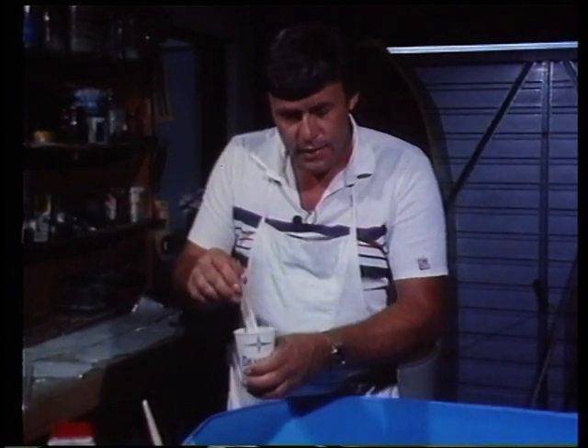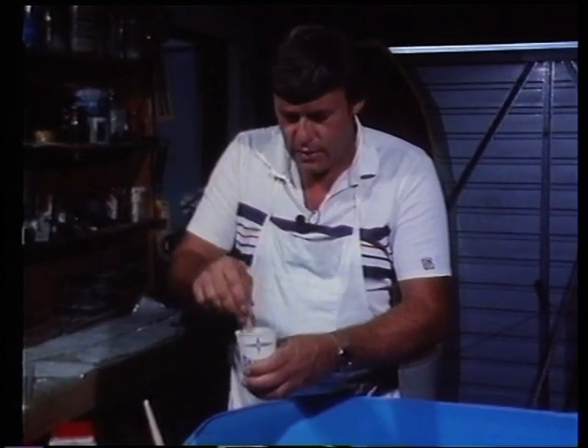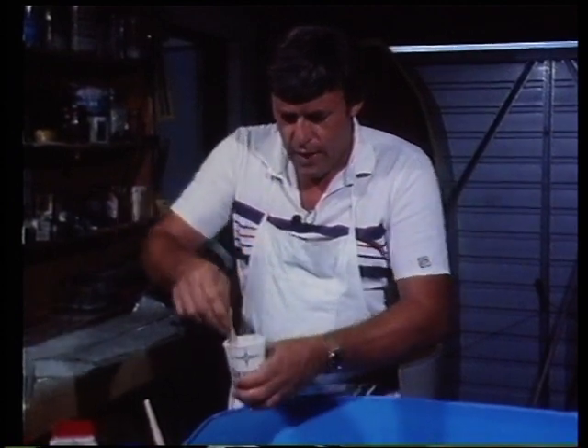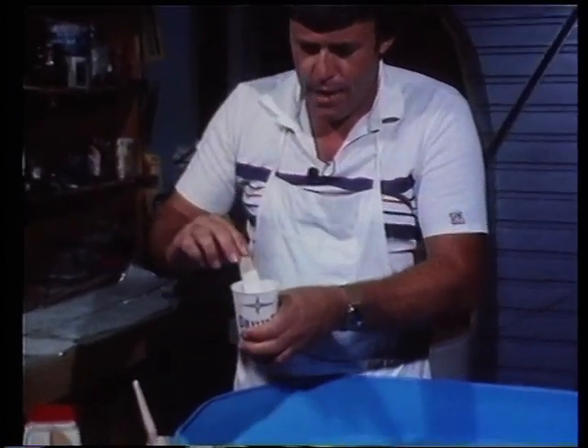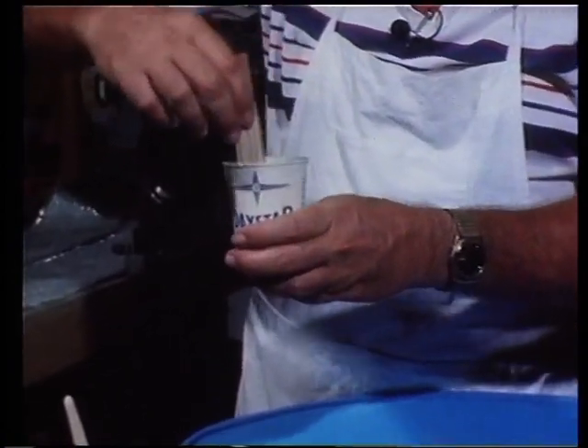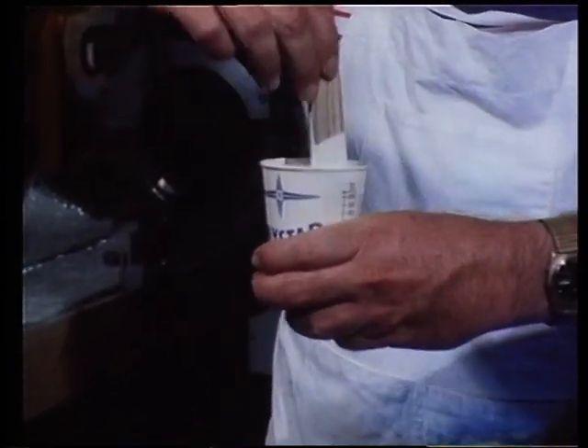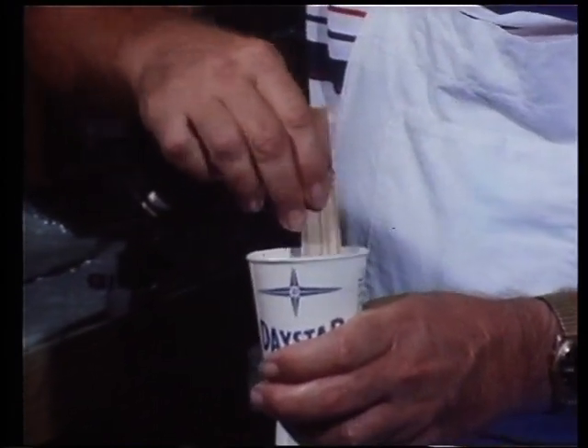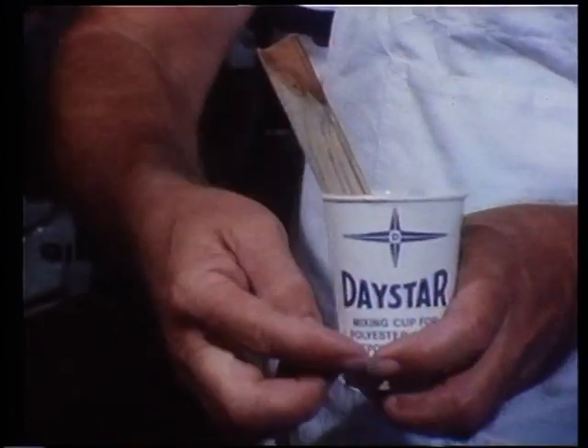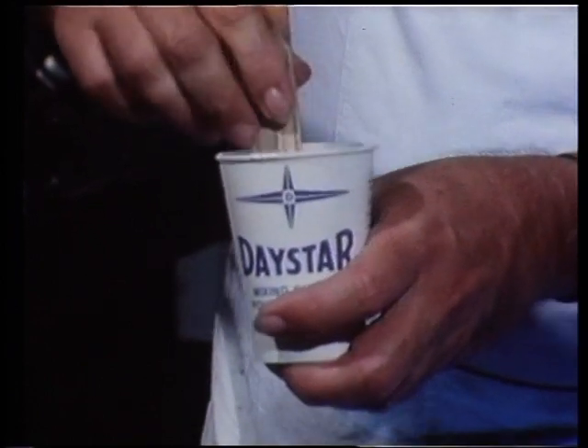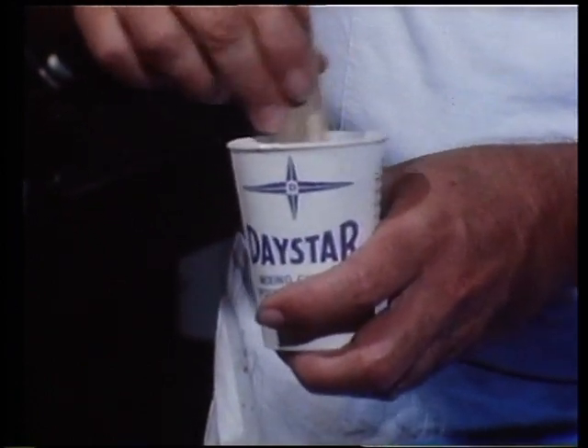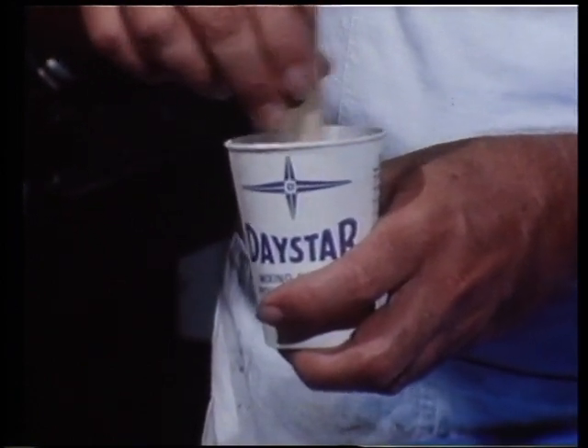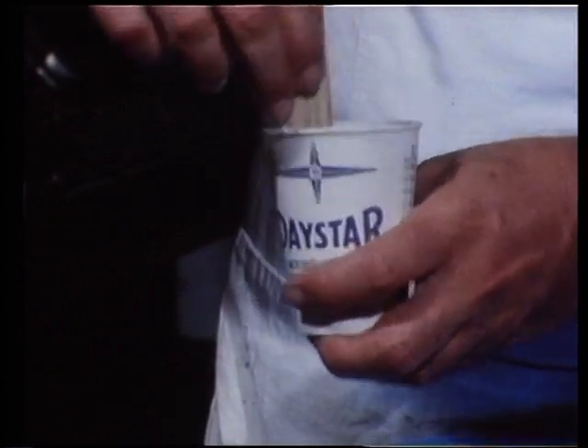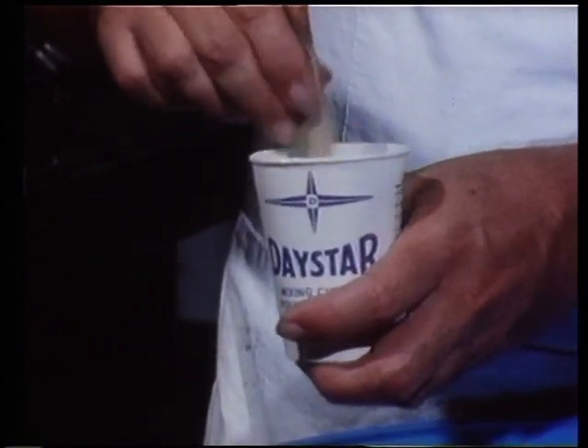So without beating it, and if you beat it you aerate it, and that's undesirable, you simply stir it around. You use your sharp cornered stick, and I mentioned earlier that the stick had to have a sharp corner on the bottom. You use it as a scraper to scrape around the inside of the container, scrape the bottom, scrape the little angle down in the bottom of the container there, and just make sure that your catalyst is completely distributed right through the gel coat. Another case in point for being thorough with everything you do.